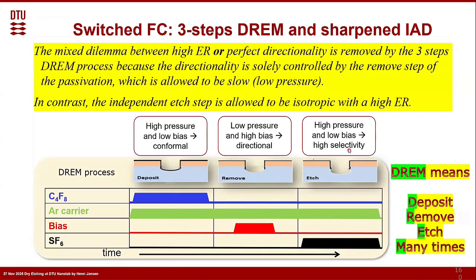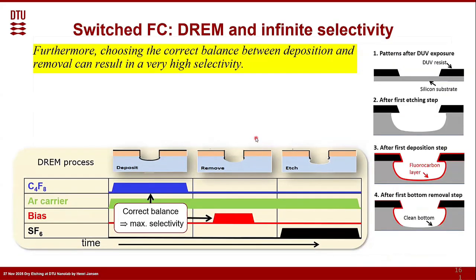And also when we etch, the final step, we can do all that without a bias. So we need the high bias only very locally to remove the deposition at the bottom. And that can be done at a very low pressure, and here we have a very sharp ion angle distribution. Furthermore, now we can choose the correct balance. We can really take this step and tune it in such a way that it is just gone.